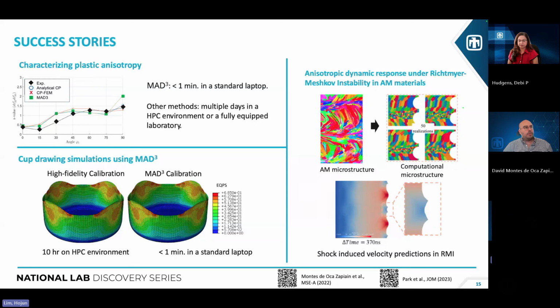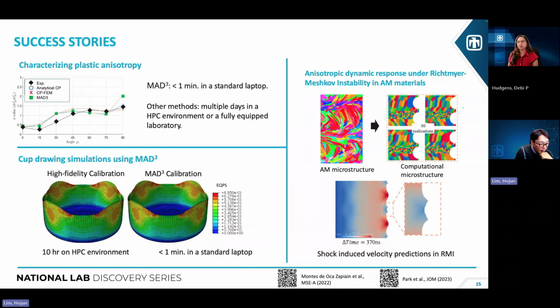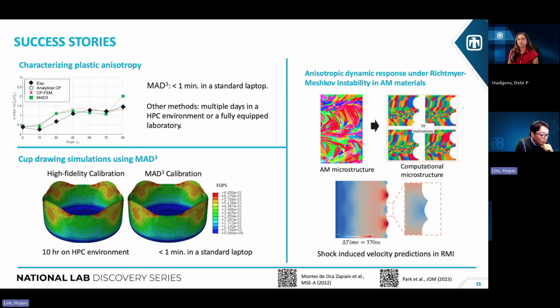Sure, yeah. So our model was trained from crystal plasticity simulations. So the MAD³ provides anisotropy coefficients for Hill 48, Yld2000, Barlat 2000, and 2004 models as well. And again, as David mentioned, in those papers from Park, you'll see how it compares with some of the parameters from the experimental characterization and from the crystal plasticity and also from the MAD³. And it agrees pretty well looking at those R values and directional yield strengths. I hope that answered your question.